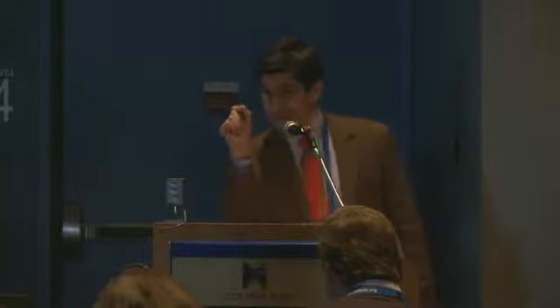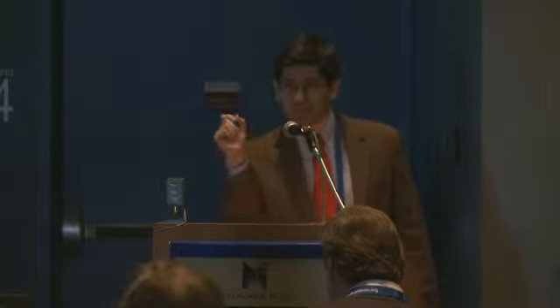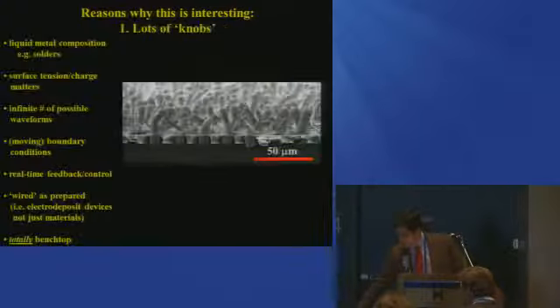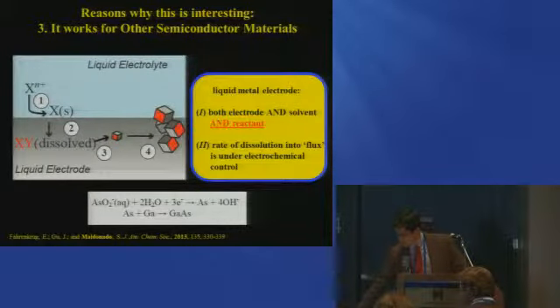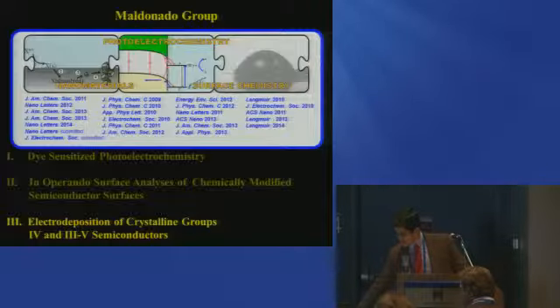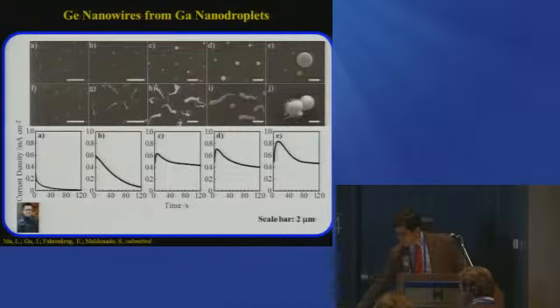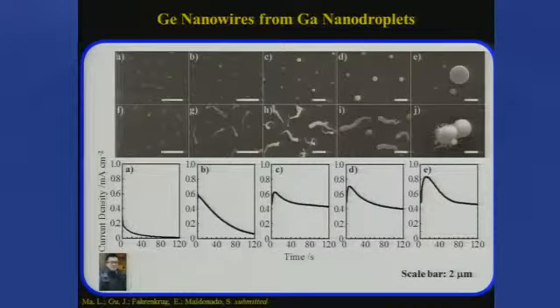Yeah, so the motivation for doing those single ultramicroelectrode experiments was to look at the transient explicitly for a single droplet, a single wire, because I think personally that would be very informative. That's a direct read of how a crystal is growing. Because we still can't get those experiments reproducible enough, we have done that by looking at arrays. So here's an array of gallium droplets that we've then electrochemically grown these germanium nanowires from.